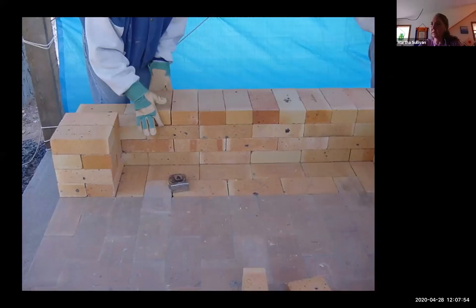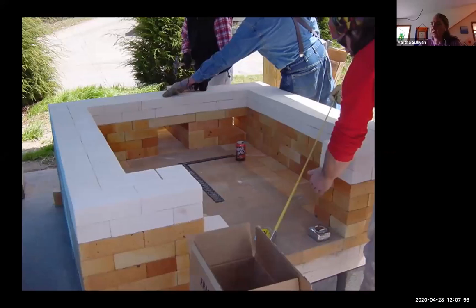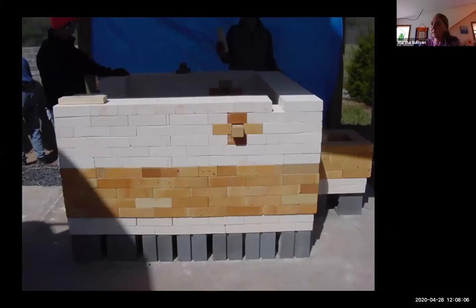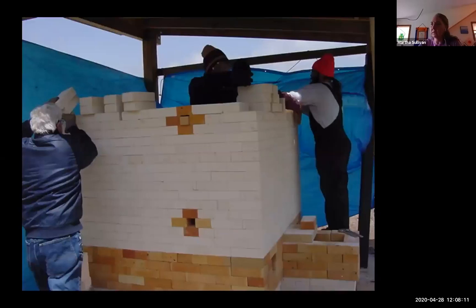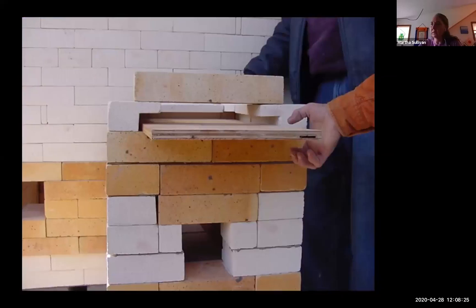So all of this kiln is a dry stack. So there's no mortar. It's loose construction. The orientation of the bricks locks the walls together. As you build up, you build in things like peepholes or burner ports. All of those things are built up layer by layer. You can see we're all wearing eye protection because all of the dust from the bricks is really aggressive. It really hurts your eyes when you get in it. And also maybe some face masks for cutting the bricks because of the silica.